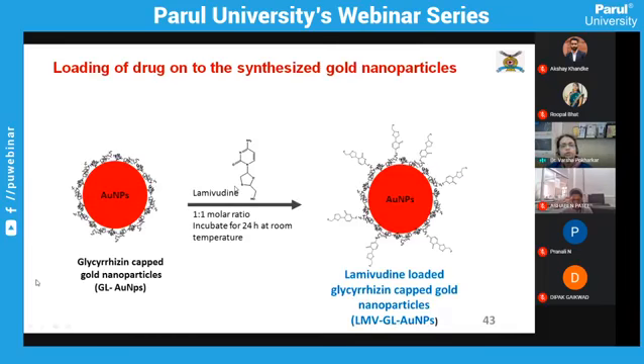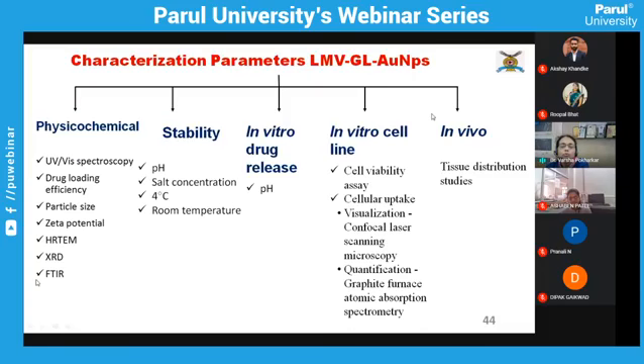Further on, we went on to loading of the drug onto the synthesized gold nanoparticles. The glycyrrhizin capped gold nanoparticles were incubated with the drug, lamivudine, for 24 hours at room temperature, following which we got the lamivudine loaded glycyrrhizin capped gold nanoparticles. These drug-loaded nanoparticles were again extensively characterized for their physicochemical properties, stability, in vitro drug release, in vitro cell line studies, and in vivo tissue distribution studies.